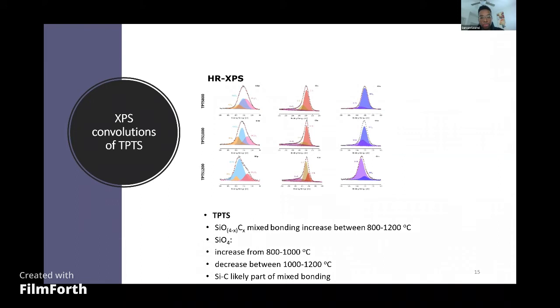From HRXPS of TPTS-derived ceramics, we're able to see that we observe an increase in the amount of mixed bonding between 800 and 1200 degrees centigrade. And those would be bonds that correspond to SiO4-x Cx. Similarly, as we look into their SiO4 bonds, which could be indicative of silica, most likely in its amorphous state, we do see a significant increase between 800 and 1000 degrees centigrade, followed by a slight decrease between 1000 and 1200 degrees centigrade. And because we don't see any convolutions corresponding to silicon carbide from their Si2p curves, it's then suggested that the SiC bonds observed from their C1s convolutions are rather representative of bonds present in their mixed bonding